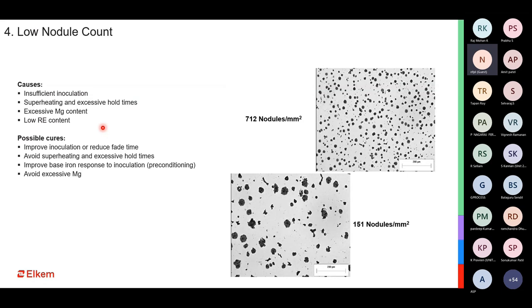So, you know, inoculation, we sometimes see that I can say that I use the best quality of FSM and I will use a not so good quality inoculant and I'll get a good casting. But in many cases, it is actually the good quality inoculant which provides you sufficient nodule count, which in turn gives you a better nodularity. So the nodularity and nodule count, both factors are interdependent on each other, and we cannot address one and let the other take care of itself. So when we are using a good quality inoculant, when we are using a good quality nodulizer, we can think or expect to get a good nodule count and a nodularity.